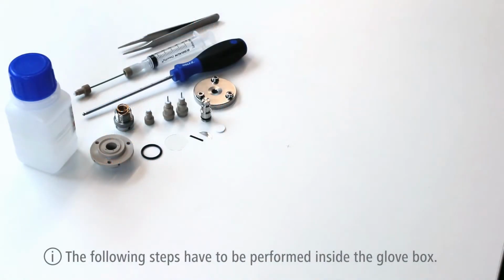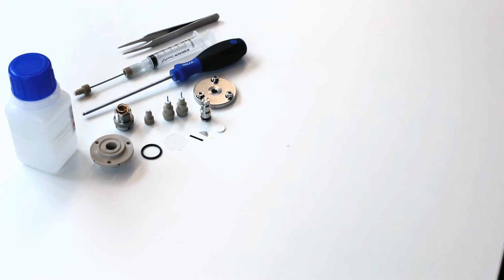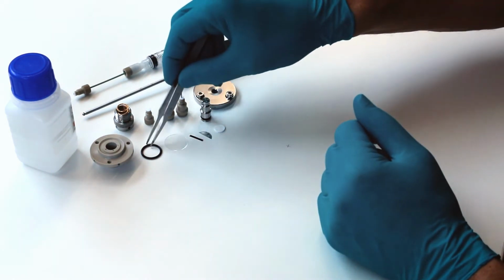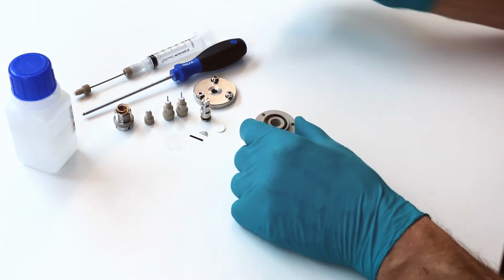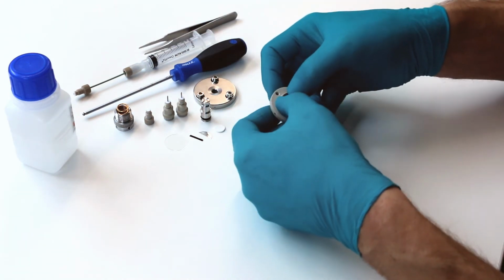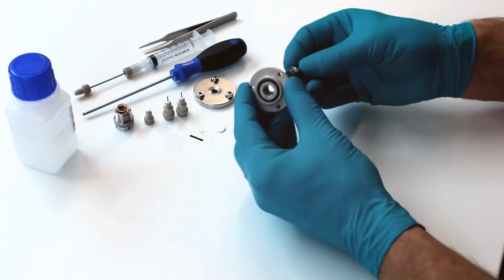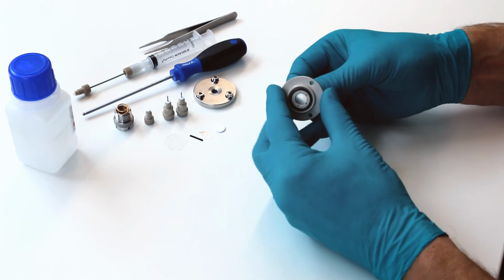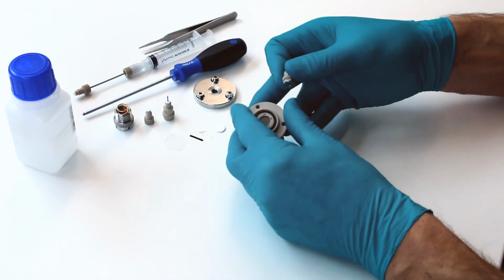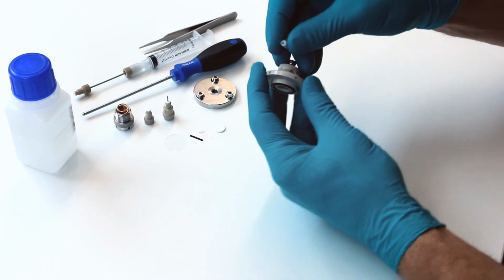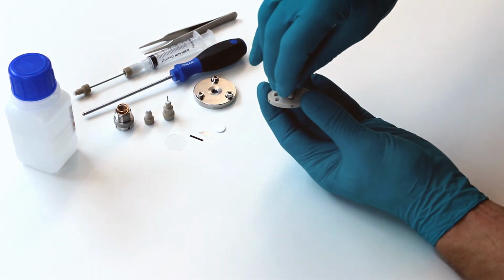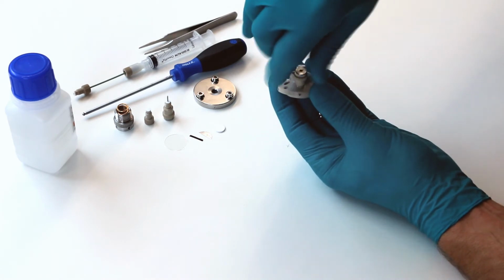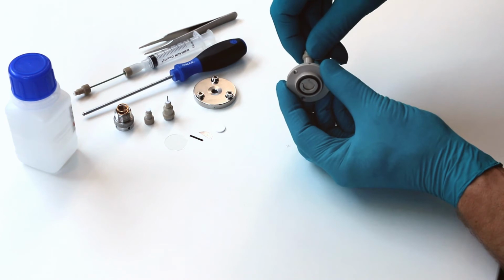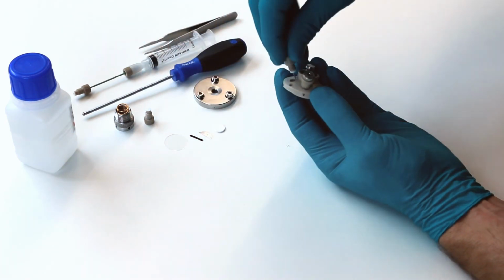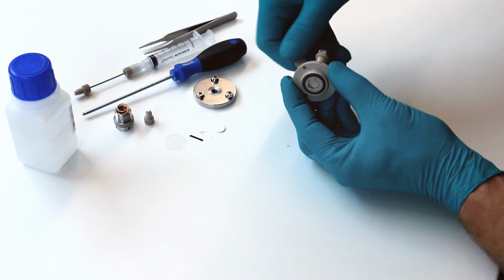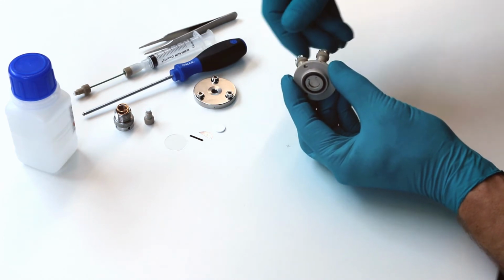Before starting the assembly inside the glove box, all components need to be dried in a vacuum oven overnight. Now, we start the assembly by inserting this O-ring seal into the cell base, then attach the central piston, attach the feed wires, the first feed wire in position B, screw in the feed wire until the tip of the wire is reaching the upper face of the cell base. Then repeat the same with the second feed wire in position A.